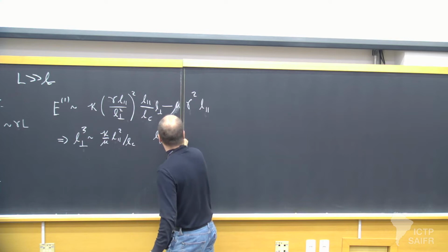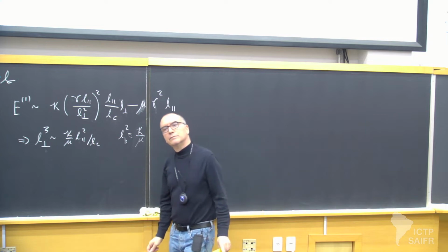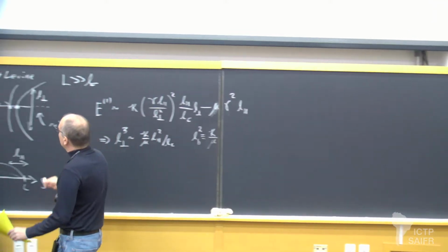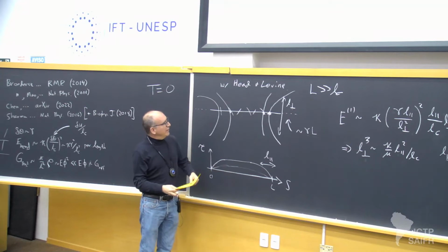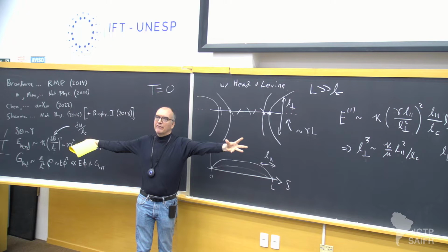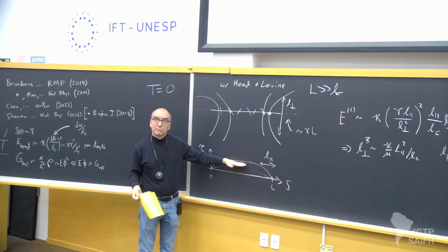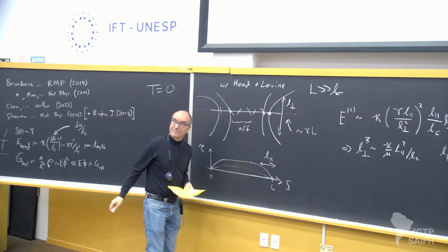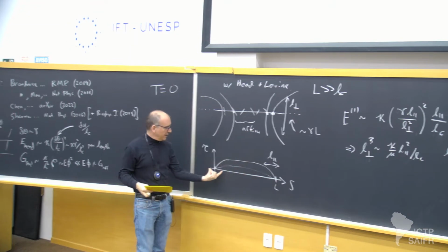Hang on. Yes, question? Yeah. I still don't have a clear picture of what you think is going on. Are we saying that it's affinely stretching at the edges? Okay, so yeah, what I'm saying here is once we realized that there would be way too much bending energy associated with these ends for a really, really long fiber to contract fully, then I have to accept that the middle of the fiber is stretched. So the middle of the fiber winds up being affine, effectively. And the non-affinity is governed entirely by these edges.